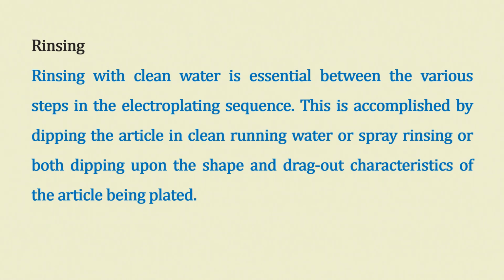So, we can also do this rinsing operation. What is rinsing? As I already told you, rinsing has to be done in clean water, correct. So, that clean water is a highly polar compound. It is known to dissolve many of the organic and inorganic compounds, and clean water is essential between the various steps in the electroplating sequence, as I have already told you number of times. This is accomplished by dipping the article in the clean running water, or I can even do the spray rinsing. Spray rinsing is very simple. You just take a hand jet, and then spray it on the metal. That also is known as spray rinsing.